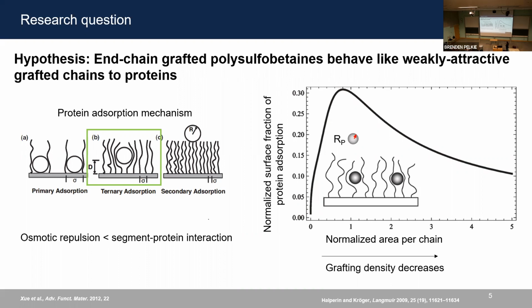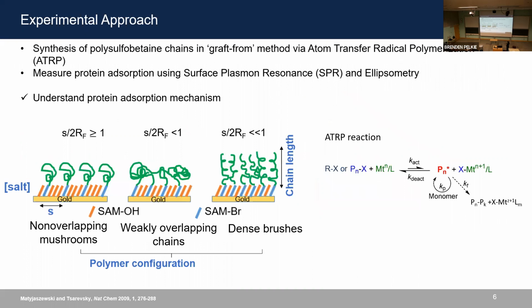And so we wanted to see that for grafted polysulfobetaines, if we change the polymer configuration on the substrate and change the grafting density, can we see this type of bell-shaped curve for different types of proteins? So in order to do that, quite simply, we synthesized the polysulfobetaine chains in the graft-from method by using atom transfer radical polymerization, or ATRP, which also allowed us to control the polydispersity as well as have good control over the molecular weight of the synthesized brush. And then we measured different types of protein solution using surface plasmon resonance and ellipsometry. So the goal was to understand the protein adsorption mechanism.